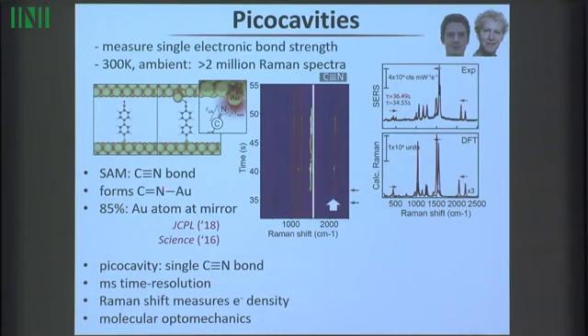And the reason that's interesting is because we can scatter a photon off that, and we have some possibility of exciting that bond. And when we do that, it starts it vibrating, but the light comes out with a slightly different color. And I can measure that color. So it's measured in a very peculiar chemist's unit, but doesn't really matter. So this line here essentially corresponds to the vibration of this bond here, that carbon-nitrogen triple bond. So this is a set of spectra, this black spectrum here, say, and I can look at it as a function of time, but that spectrum tells me all the bonds, the vibrational energies in that molecule.